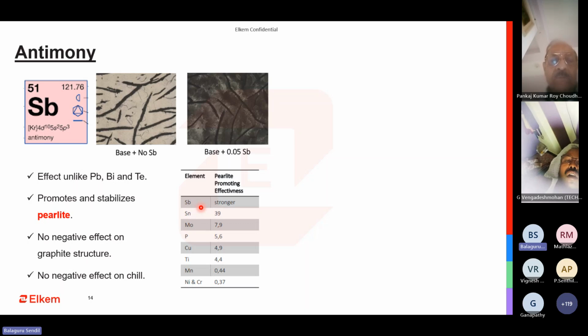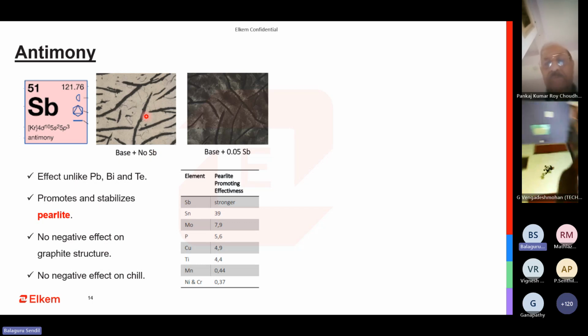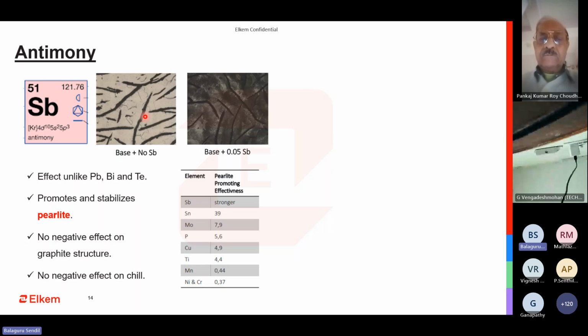So when you are seeing a rise in antimony from your liquid metal, it is advisable to keep lowering the manganese or copper to make sure that you don't overdo it. So there is no negative effect of antimony on the microstructure for gray iron with respect to the shape and size, as well as on the chilling tendency. It just promotes pearlite. The only thing it does is that, and which is manageable.